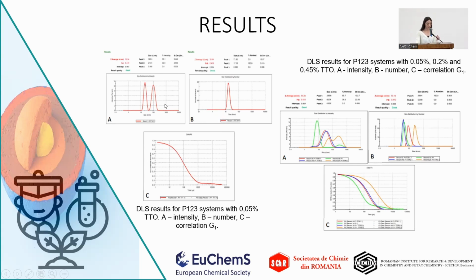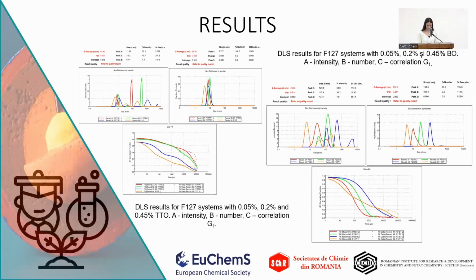The much bigger size is actually in a lower number. As for the rest of the systems, for the P123 systems, the increase in concentration of essential oils actually leads to an increase in size of the aggregates, which means that we successfully encapsulated the essential oil in the aggregates.